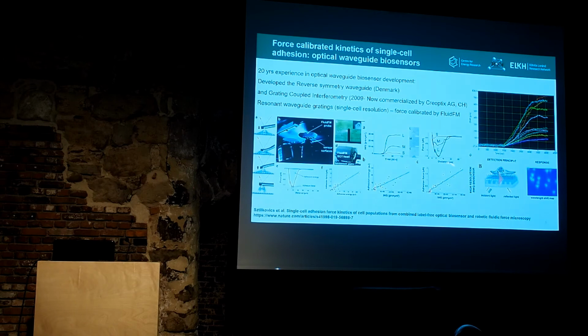And this technology is based on optical waveguides. The optical waveguide is a thin layer with a high refractive index, and basically in this thin layer you can trap the light. So the light can propagate in this thin layer by total internal reflection. And if we employ a grating structure, we can couple the light into this thin layer. And during propagation, this propagating waveguide mode creates a so-called evanescent wave near the interface.